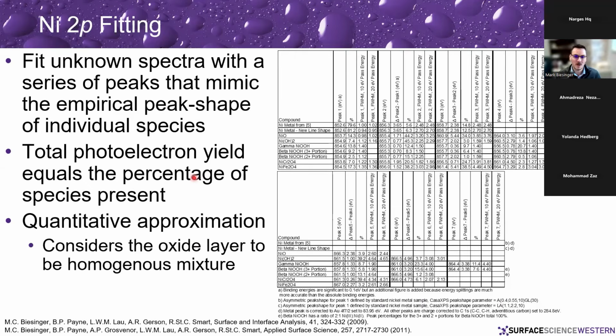And so if we go through a whole bunch of different materials, we can develop these sorts of models that mimic the peak shapes that are present. We do it this way so that it gives you some leeway in how you fit these things. Everyone's spectrometer is not the same, and things will be taken at different resolutions. So doing it this way allows you to loosen some constraints if you need to, for example on full width half maxes of the very sharp peaks. You may not get as sharp a peak if your spectrometer is older or if you're using lower resolution settings. So these sorts of tables allow you to work with those issues, as opposed to just using a straight copy and paste of a spectrum, which is used in other systems, things like IR. And so we do all this, and we set up these fitting routines.